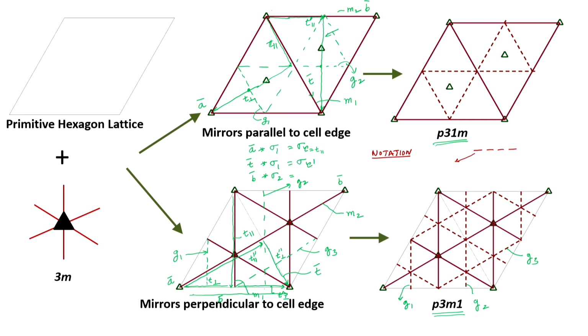The first symbol in the case of plane group will be either a lowercase p or a lowercase c. P stands for primitive cell, C stands for the centered cell. So, whenever you see a notation which starts with a C, then very clearly we are going to talk about only centered rectangular lattice. So, in fact, we are talking about a rectangular lattice. If P, then it would be one of the other primitive lattices, which one can understand by seeing the rest of the symbols.